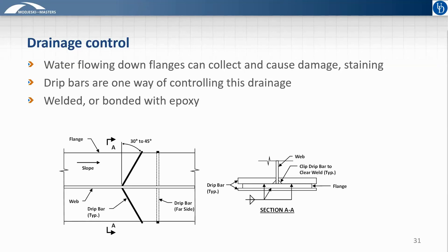So as what's shown on the left here, you have drip bars on the top of the bottom flange, angled at 30 to 45 degrees, and therefore any flow coming down the slope of the flange would be diverted off the edges of the flange. And then underneath, you can just put a drip bar straight across, and that prevents any water flow that's attached itself to the bottom of the bottom flange from continuing past that point.